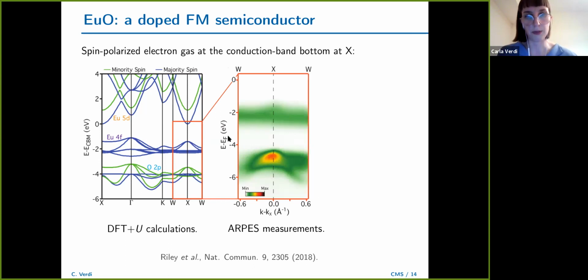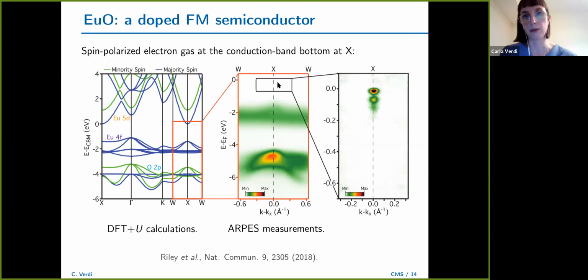Of course, it's kind of blurred, but you see it sees the same features that we see in our ab initio band structure. And then if you zoom here at the bottom of the conduction band, where it looks like there's nothing, there is actually some signal. And you see there is the main band at the bottom. And then there are these satellite replicas underneath again.